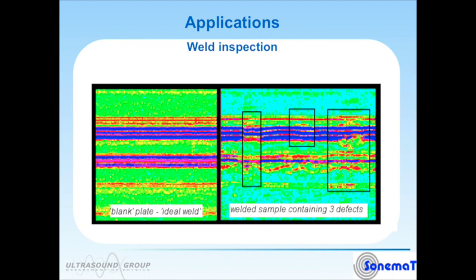So we can use this as a rapid screening method. We can do some defect sizing. We can also do some defect positioning within the depth of the weld by looking at how each wave mode is affected. This weld that was scanned here was over 30 centimeters long and was done in under 1 minute.